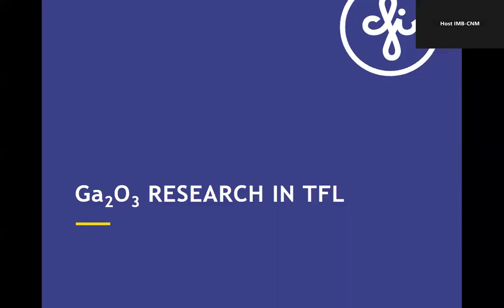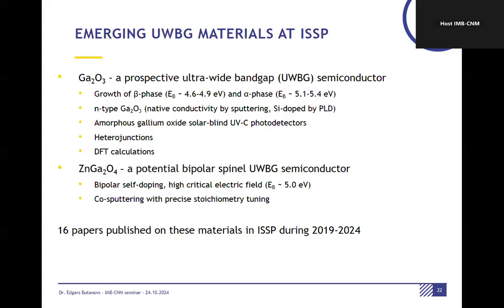Okay, so what we have done so far in our institute. I already mentioned some things. But mainly we work with both beta phase and alpha phase thin films. We do some N-type films with PLD. We do amorphous gallium oxide for UVC detectors, and we plan to do some more heterojunctions. I'll briefly mention we have collaborators who do DFT calculations, so that helps with understanding some basic defect structures. We also worked on interesting spinel materials, gallates. There is some possibility of bipolar doping by controlling these so-called antisite defects in spinels. And it's interesting for power devices, but it's not been explored that much.